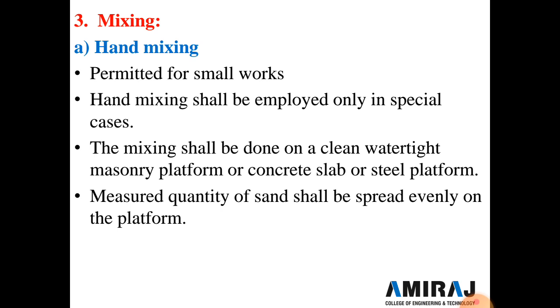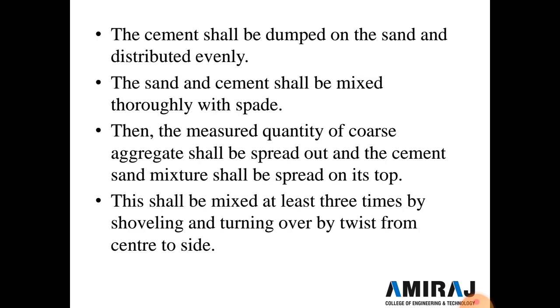The mixing shall be done on a clean watertight masonry platform, or a concrete slab or a steel platform, which is generally used during hand mixing. The measured quantity of sand shall be spread evenly on the platform, and the cement shall be dumped on the sand and distributed evenly. The sand and cement shall be mixed thoroughly with a spade, turning the mixture over and over again until it is of even color throughout.